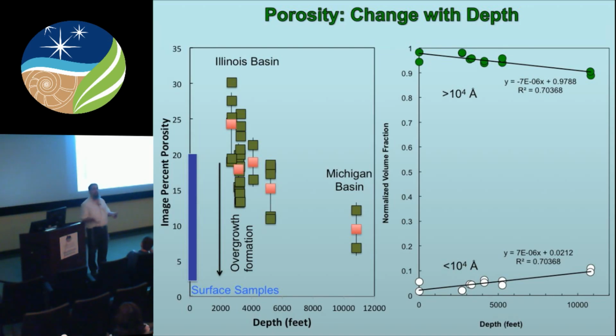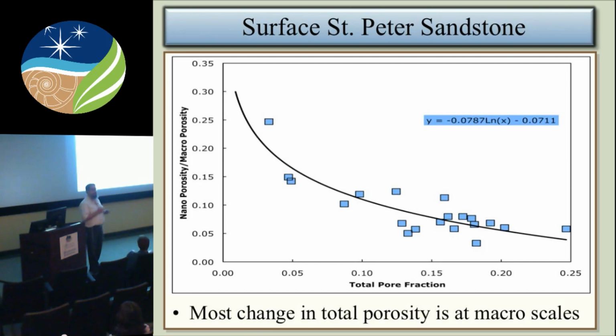The other possibility, however, is that this may reflect flow paths through the sample. In order to get something to precipitate, you've got to get the material to the pore space. So it may be that in a sandstone, the larger pores are filling first because this is primarily a transport-driven process. Whereas in the shales with maturity, and we've also seen this in metamorphic samples, it may be more of a reaction precipitation process. So the change may have to do with the process as much as with the transport within the rock.